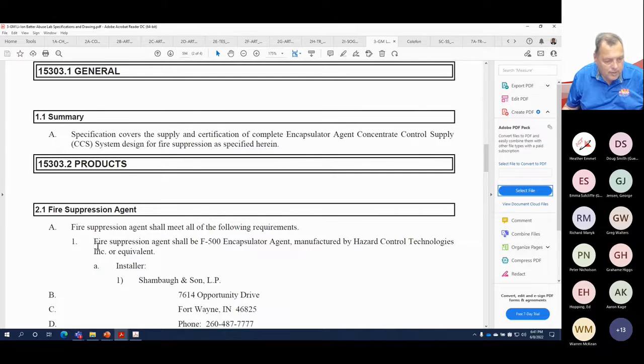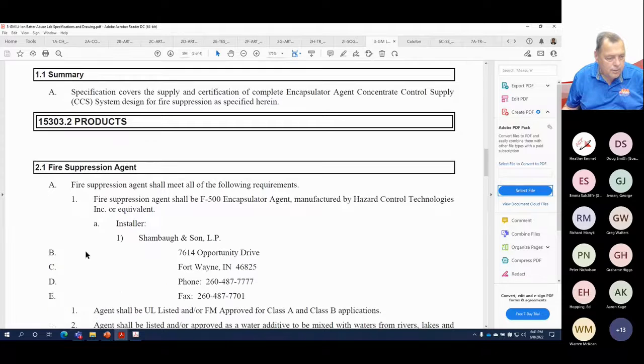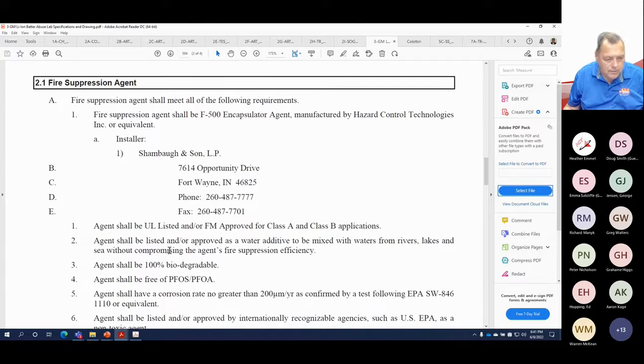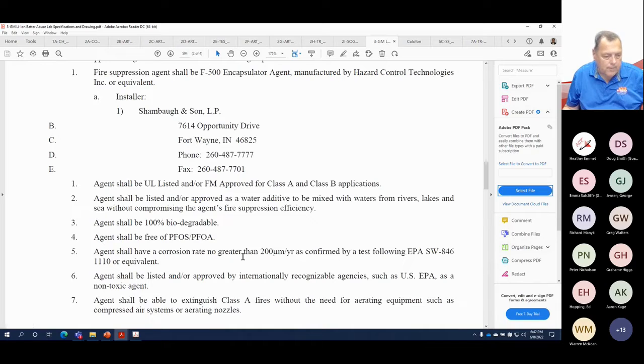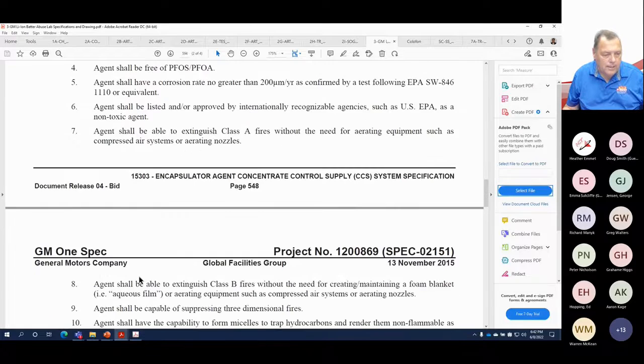So the fire suppression agent is F500, manufactured by Hazard Control Technologies. The installer of the system was Shambaugh and Sons. The agent was UL listed. It's listed and approved for mix with plain water, rivers, or seawater. 100% biodegradable. The agent is free of PFOS and PFOA. The agent had to have a corrosion rate less than 200 per year. So this is just the specification on the agent.